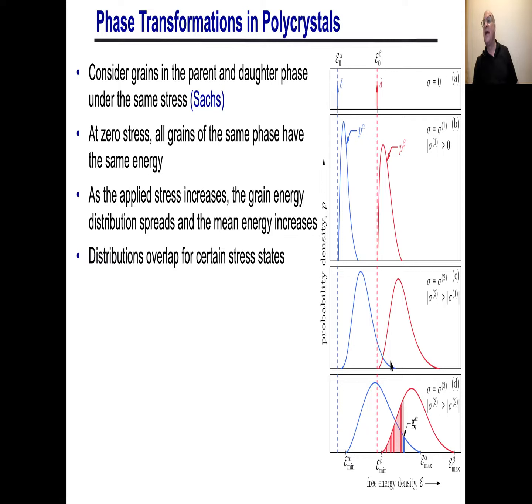Now, if I look right here for a minute, it says a grain here in alpha would lower its energy if you allow it to transform to a beta phase, which has an orientation corresponding to this energy. So there's a range of orientations that thermodynamically an alpha grain can transform to in beta. So any of those orientations. But if we say there's only particular orientation relationships, that means for every grain, depending on which transformation we're talking about, there are 12 or 24 different possibilities. And then we look at all possible orientations of grain alpha. So if a grain in alpha has this energy, it can then transform to specific orientations here, as long as they're underneath, they're under here. Okay, so which specific ones just depends on what orientation relations we specify.